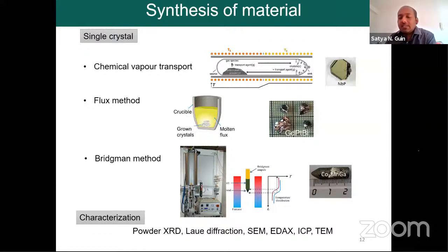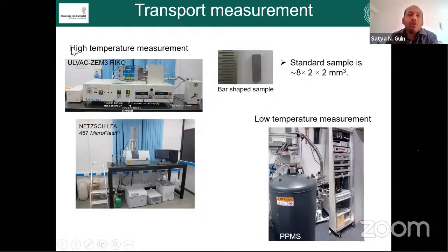After the synthesis, we go for the measurements. For high temperature measurements, this equipment is generally used, and for thermal conductivity we can use LFA. For low temperature, if you want to know the refrigeration property of the thermoelectric material, you can do low temperature transport in the physical property measurement system. Generally, standard samples are required for the thermoelectric measurements, and this is the dimension generally used.